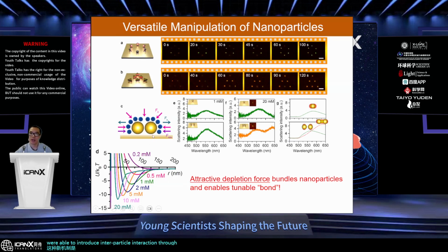Another interesting thing about this new mechanism is that we are able to introduce interparticle interactions through what we call artificial bonding. This artificial bonding enables us to bring the particles together and make them stay there, stuck together. In conventional optical tweezers, whenever we turn off the laser beam, the particle goes back to Brownian motion again. When you bring two particles together and try to stick them to create a new material using these particles as building blocks, you have to introduce a very special interaction. But in our system, it becomes an intrinsic force embedded into the system, which we call the attractive depletion force.